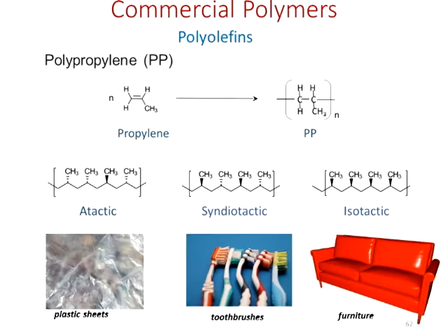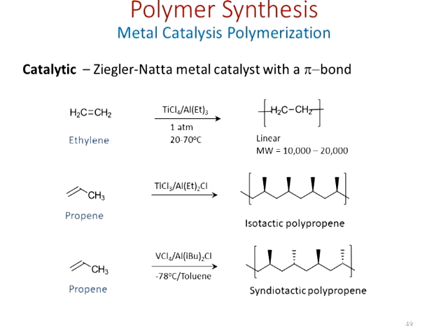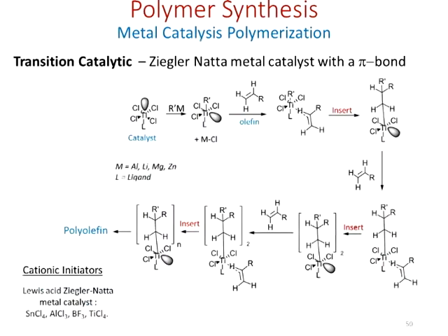Then you might have a syndiotactic, and in the case of a syndiotactic application, it's made using what's called a Ziegler-Natta catalyst. Okay, and when you think of the Ziegler-Natta catalyst, there are several varieties of them. But for the syndiotactic polymer, typically there's a vanadium catalyst that's used with a co-catalyst that has an aluminum metal in it, and this gives you this stereospecific polymer where the olefins interact with the metal surface on one side to form a complex.